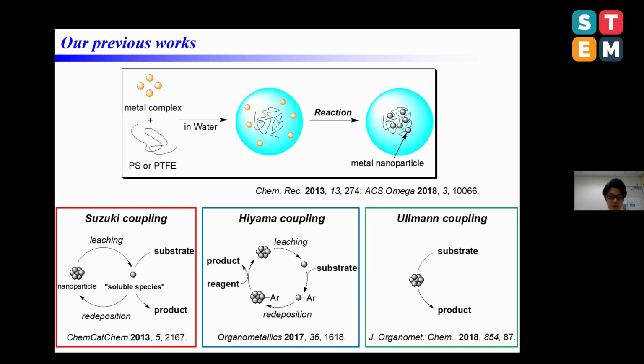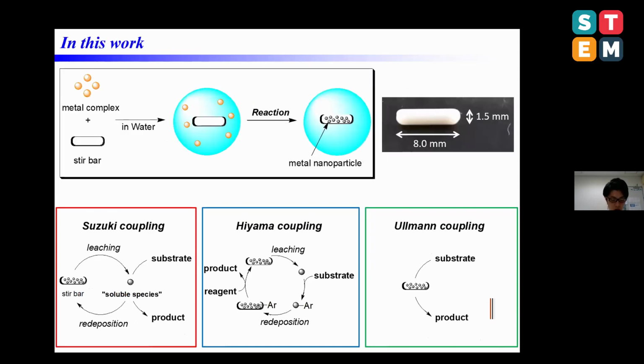In the case of the Hiyama coupling reaction, it was confirmed that the reaction proceeded alternately in water and on the surface of the nanoparticles. And in the Ullmann coupling reaction, the reaction proceeded only on the surface of the nanoparticles. Based on this background, we thought that it would be possible to reuse ppm level metal species by using a stir bar as a support. And the purpose of this study is to clarify the conditions under which metal nanoparticles on the stir bar can be reusable.